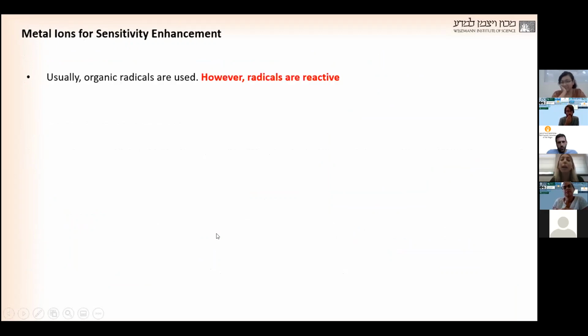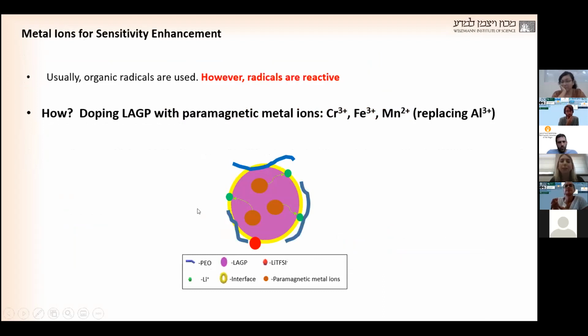Usually people use radical solution, but the problem that we have is that it's really reactive. So we change the properties of the material. Our group is the first one to use paramagnetic metal ions for inorganic oxide materials, solid materials, and we use it for LAGP. We dope the LAGP with chromium, iron, and manganese that can replace the aluminum in the LAGP. And they have unpaired electrons that can transfer their polarization to the nucleus inside of the interface.